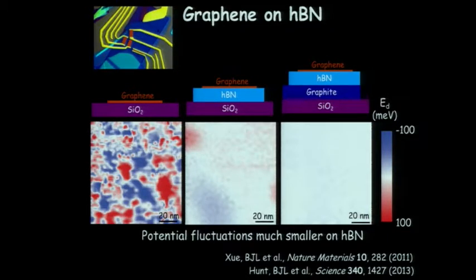result. The one issue I think with using thick HBN is HBN does have defects in it, right? So they're much lower density, but they are present. So when you start using too thick of HBN, you sometimes see the defects in the HBN instead, whereas I think if you go here, you're probably going to, in general, have a better result because you're only 10 nanometers of HBN. Right? So I think actually this red dot here may actually be a defect in the HBN and not from the silicon oxide.